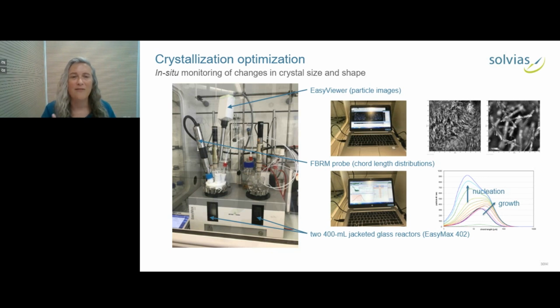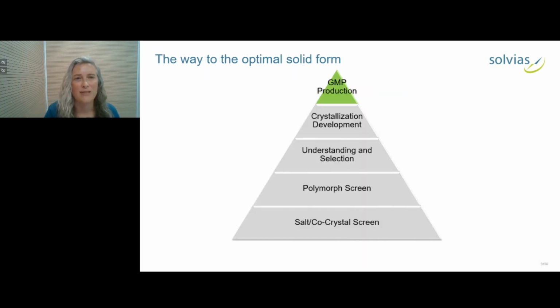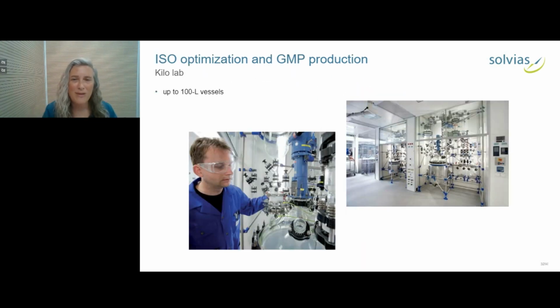And using this kind of feedback, we can vary parameters, we can control the dosage and the temperature and the stirring rate, and develop a controlled crystallization process. And once we have that process, we can transfer it to our kilo lab. So we have an ISO and GMP kilo labs where we can produce under GMP in up to 100-liter vessels. We have some stages in between.